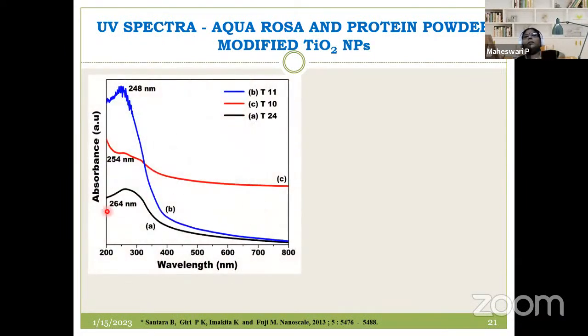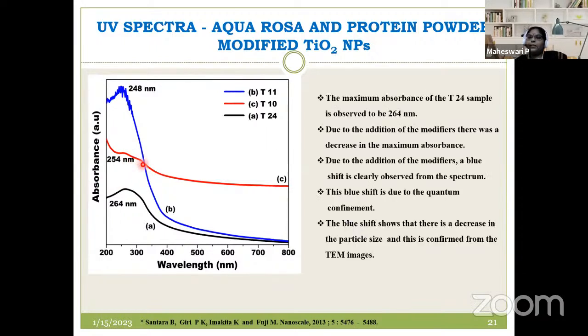Now, in the case of UV spectra, we were able to see that in the case of the pure titanium dioxide which we have synthesized, the maximum absorbance is at 264 nanometer. Whereas in the case of protein powder and aqua rosa, because of the modification, we were able to see a decrease in the maximum absorbance. And also we can see a shift to the blue, which we call a blue shift. This blue shift happens because of quantum confinement, where the size of the particle becomes very small. And this we can clearly confirm with the TEM images which we have obtained.